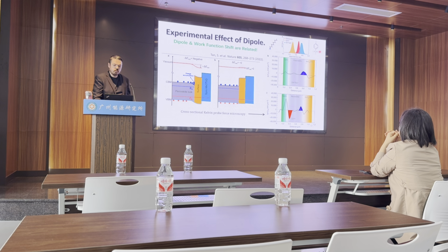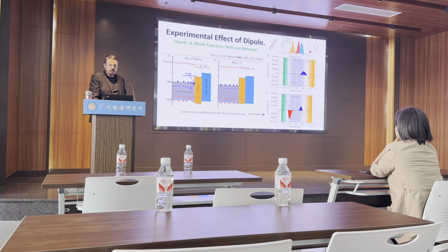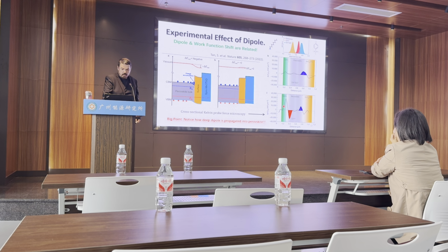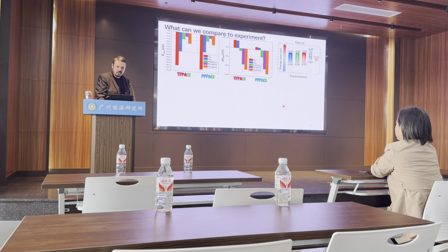So basically they checked what the difference is when they varied the counter anion. So this is tosylate, and then this one they did just iodine. In the case of iodine, we get the bad result of accumulating charge at both interfaces. With the tosylate, the problem is not so big. So we don't want negative charge at the HTL perovskite interface, obviously, because that will cause problems. So the big point is to check how deep the dipole propagates into the perovskite. The whole wafer, that's pretty unusual.